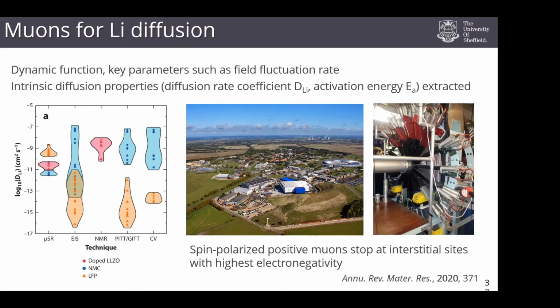And that's because there's no standard way of doing an impedance measurement for the battery community. Each user might do it slightly differently, and they may press the pellet slightly differently. And every time you press the pellet, your grains interact with each other. And every time they interact, you've got a new interface that is going to be a challenge for lithium ions to get across. So we've turned to antimatter, which is quite exciting, and it is.